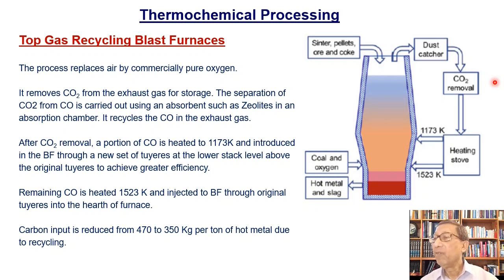And the second thing we are doing is reducing the energy needed for the production of iron by taking out the nitrogen. Nitrogen does not have to be heated because we are not supplying any nitrogen in this process. And the carbon consumption will be reduced from 470 to 350 kg per ton of hot metal due to recycling, because we are recycling carbon monoxide.